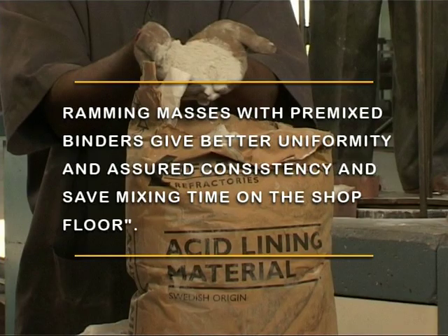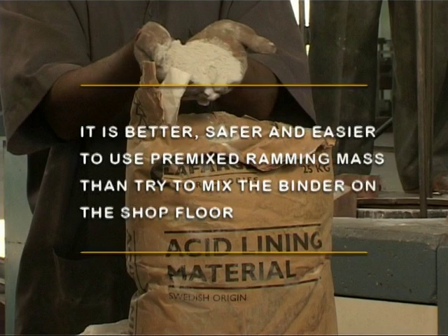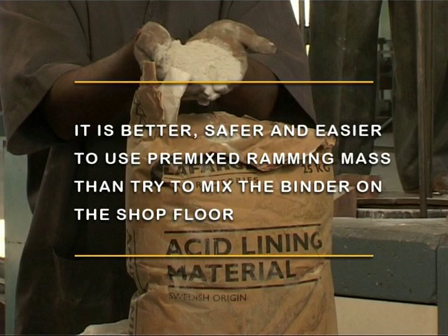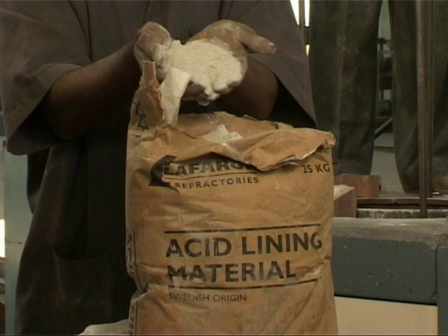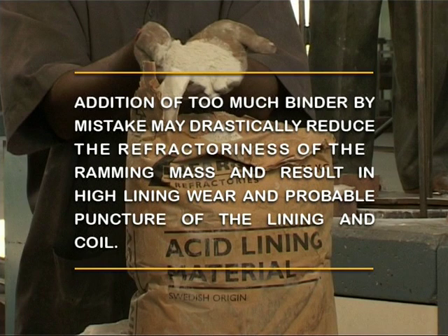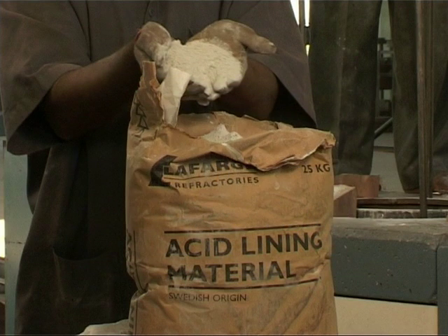Ramming mass with premix binders give better uniformity and assured consistency and save mixing time on the shop floor. It is better, safer and easier to use premixed ramming mass than to try and mix the binder on the shop floor. Addition of too much binder by mistake may drastically reduce the refractoriness of the ramming mass and result in high lining wear and probable puncture of the lining and coil.